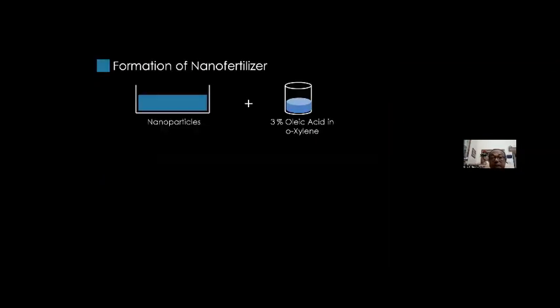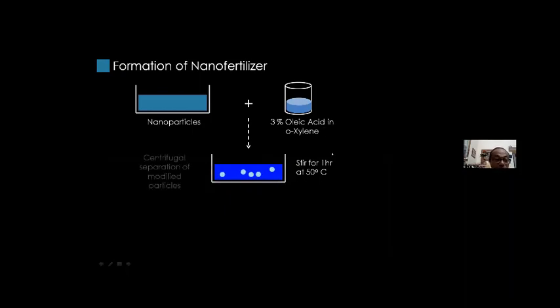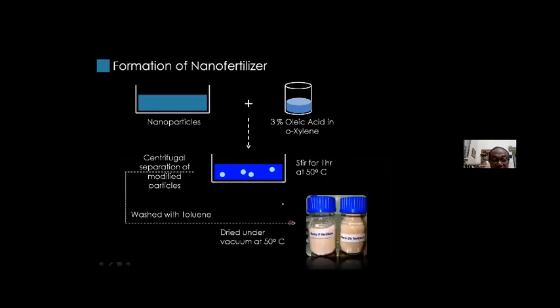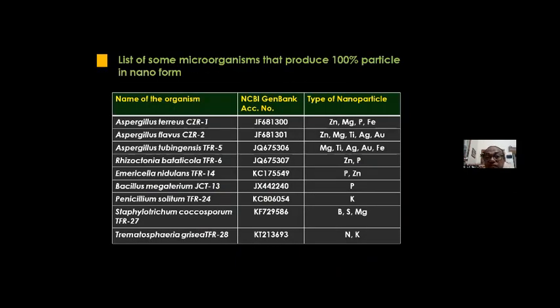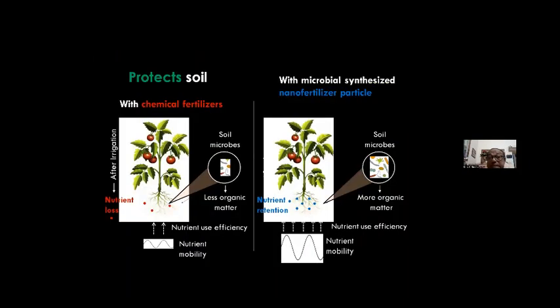So you can use this nanoparticle as liquid, or if you like, you can use these nanoparticles as solid, by treating with oleic acid and xylene, stirring for 1 hour at 50 degrees centigrade, and then going for centrifugal separation of the modified particle, then washing with toluene and drying under vacuum at 50 degrees centigrade, and you will get solid nanoparticles also. So both ways you can use it. We have developed so far 73 different organisms whose proteins can be used to produce whatever nanoparticle is needed for plant development. I am showing some examples here. These are the organisms that are producing this type of nanoparticles from their respective soil solution through the action of their proteins.